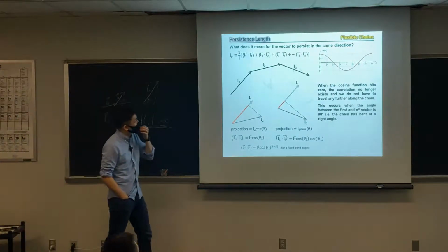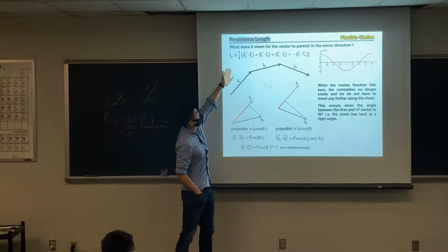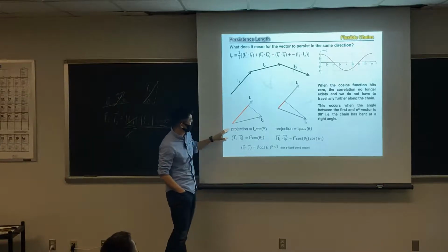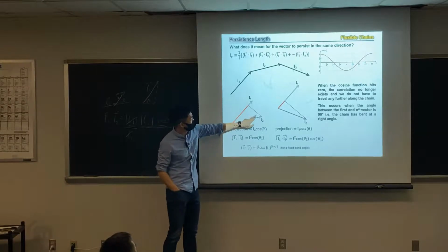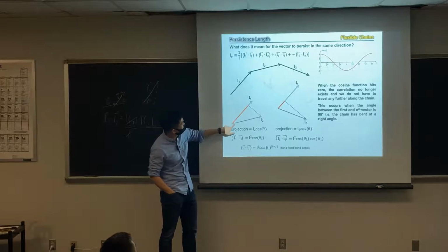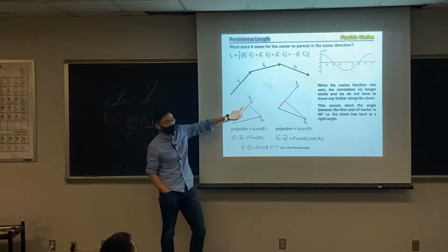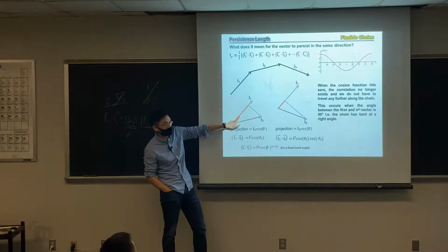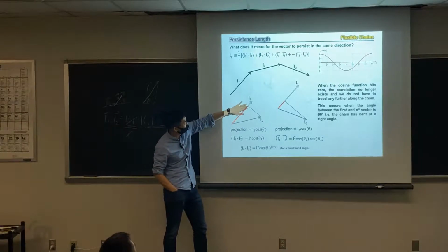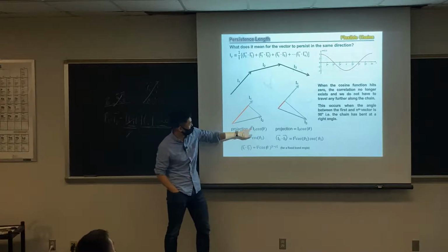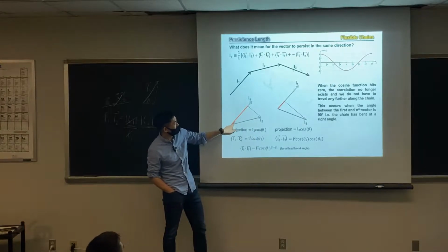I already alluded to this a little bit. That's the definition of persistence length, and this is looking at the projection of L2 along the L1 direction. The directionality: if L2 follows the majority of that direction, that means the angle of L2 will be defined fairly close. This red line is defined as the absolute value of L2 multiplied by cosine theta. Theta is this angle.